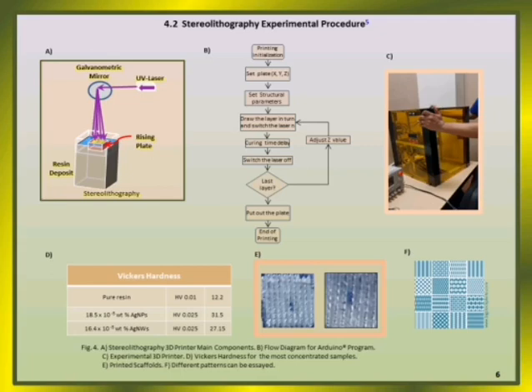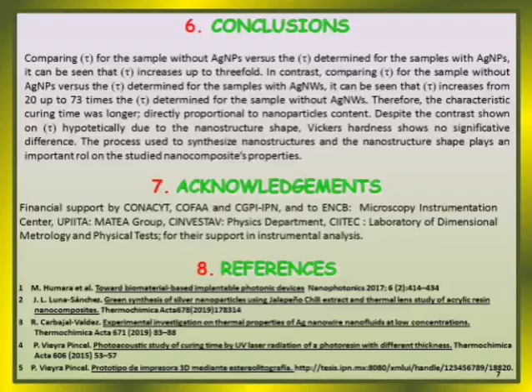After testing Vickers hardness, we found that the cured resin with silver nanostructures presented a hardness twice larger than the hardness of the resin without nanostructures. But there is no meaningful difference among the hardness found for the nanocomposites with round silver nanoparticles or with silver nanowires. In conclusion, it was found evidence to confirm that the nanostructure synthesis process and the nanostructure shape are important influences on the characteristic curing time. Preliminary tests of Vickers hardness show no meaningful effect due to the nanostructure shape.